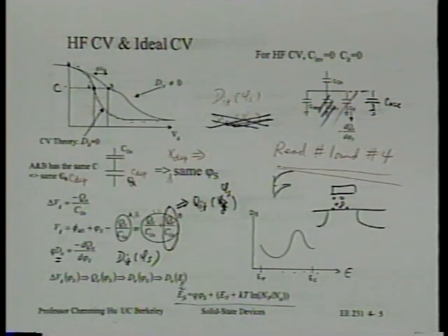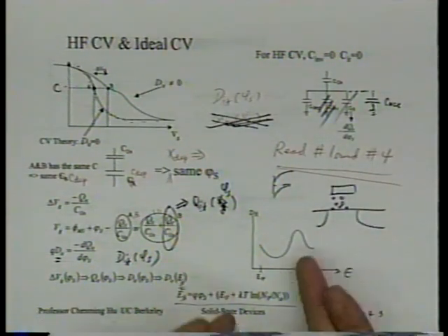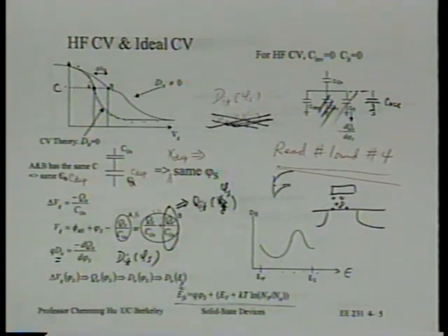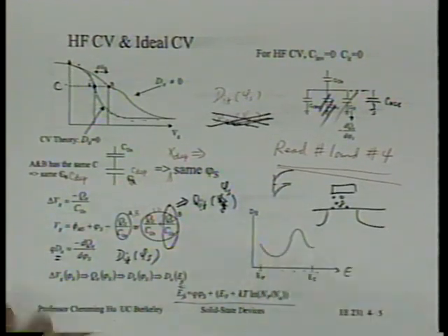It appears that the so-called process traps are continuous, but we already know one particular example. We know after stress there's one particular peak, and certainly one can visualize other types of chemical bonds that may give you discrete energy. So there could be a discrete spectrum superimposed on a continuous background. With a fresh sample, you usually expect one smooth curve.